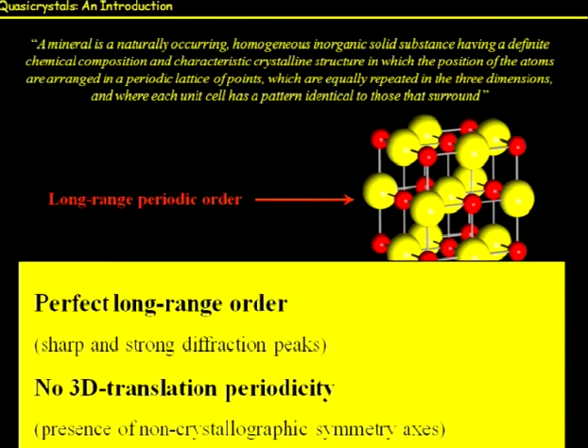The fact of having a long-range order means that if I carried out an X-ray diffraction study, I will see sharp and strong diffraction peaks, as in the best crystalline material. But having no 3-dimensional translation periodicity means that I can see non-crystallographic symmetry axes. Well, so what about non-crystallographic symmetry axes?